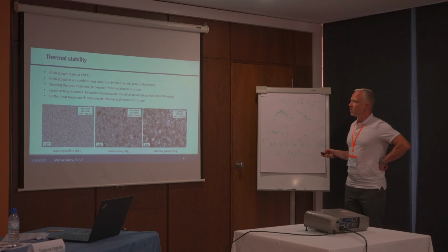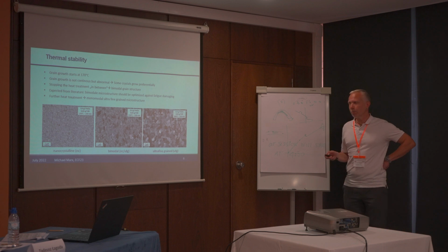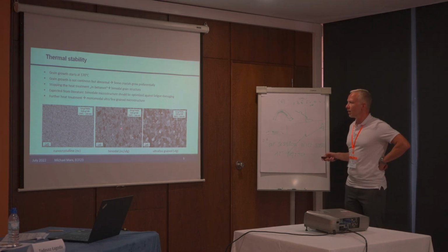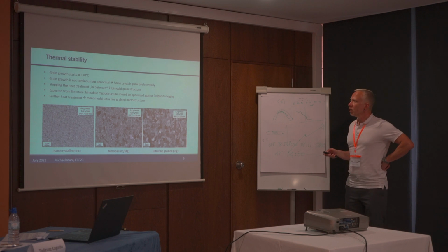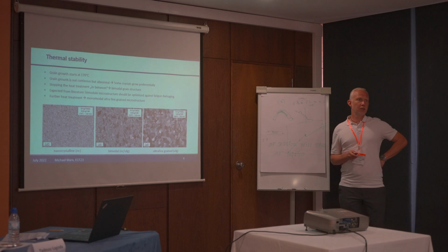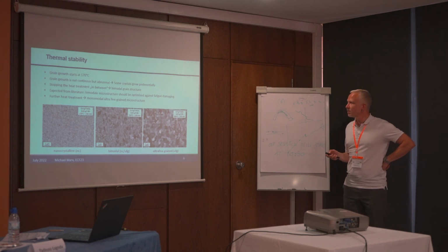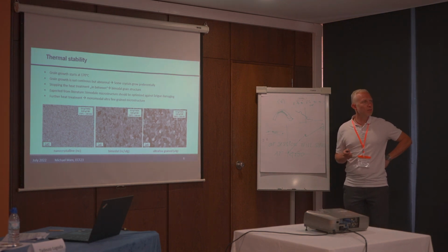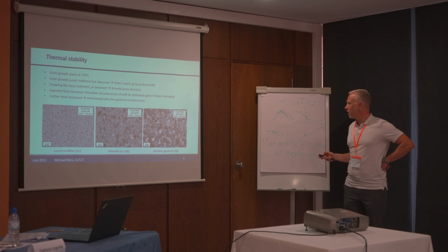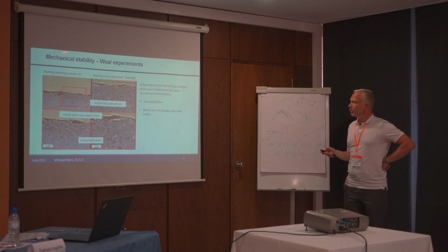You can also use this to produce a bimodal grain structure. You can stop a heat treatment in between, and then you have a nanocrystalline ultrafine grained microstructure, which from literature is expected to be optimized against fatigue damaging. For further heat treatment, you get monomodal ultrafine grained microstructure, as you can see here, and for further heat treatment at higher temperatures, you will get a second stage of grain growth, again abnormal grain growth with some grains growing in the order of some tens of microns and the others remaining in the ultrafine grained area.